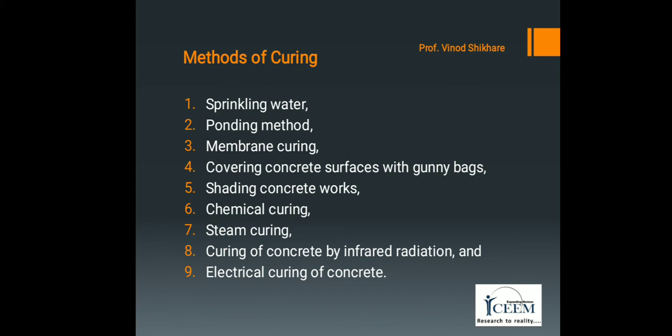The next method is chemical curing, which is comprised of spraying sodium silicate solution. About 500 grams of sodium silicate mixed with water can cover one square meter of surface area and forms a hard and insoluble calcium silicate. It actually acts as a case-hardener and curing agent. The application of sodium silicate results in a thin varnish-like film which also fills pores, sealing the surface and preventing the evaporation of water.